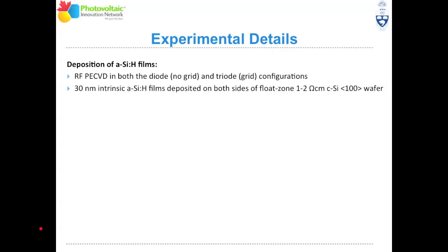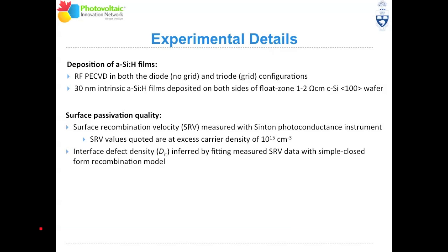So to demonstrate the validity of this method in terms of getting really good, effective hetero interface properties, we performed an experiment where we deposited 30 nanometers of intrinsic hydrogenated amorphous silicon on both sides of a crystalline silicon wafer. And we used both the conventional diode RF PECVD method and the triode, which is with the grid configuration. We measured the surface passivation using a Sinton photoconductance instrument to measure the quality of the passivation.